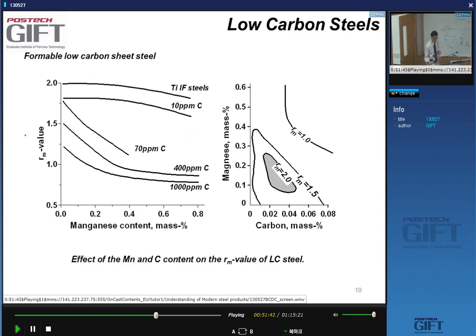Now let's have a look at the compositional effects, the effect of composition on deformability. It turns out that things are a little bit more complex than you'd want. And it's due to the following. When you let carbon precipitate, so it goes from carbon in solution to a piece of cementite, Fe3C, yes? It turns out, and what you want to do to get the high, good textures, is you want this carbon content to be as low as possible, preferably no carbon in solid solution.